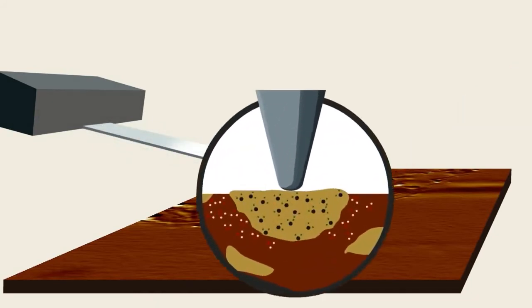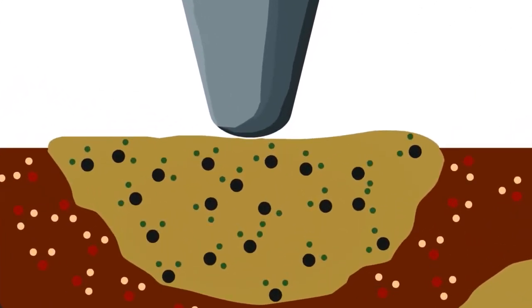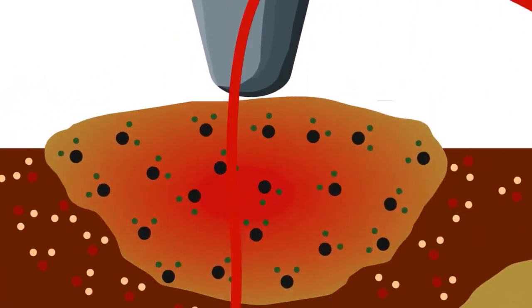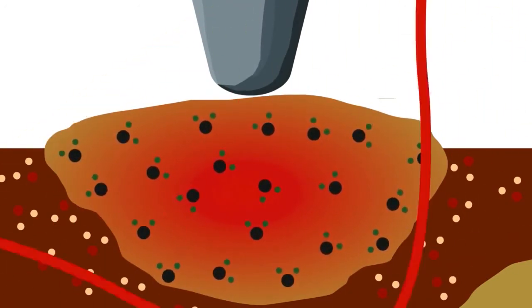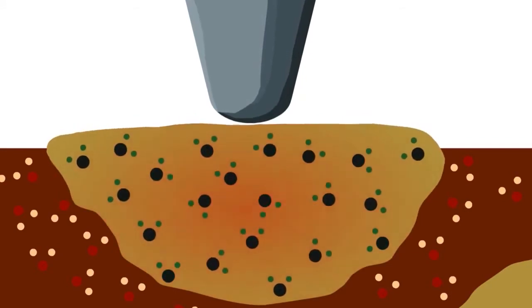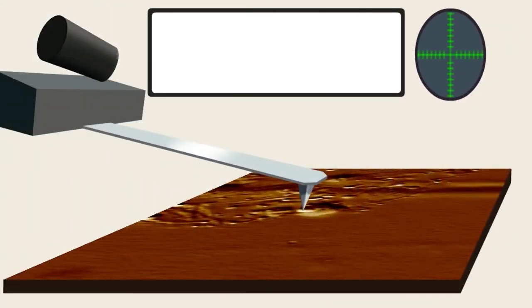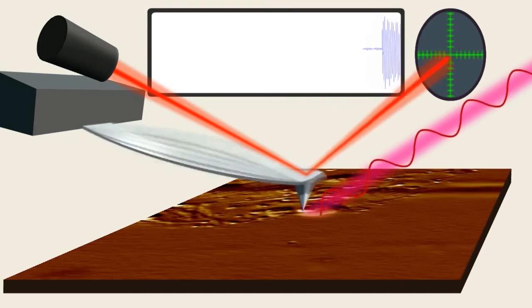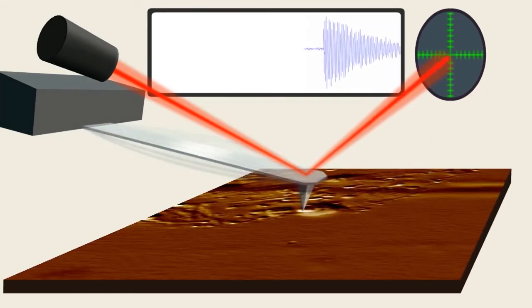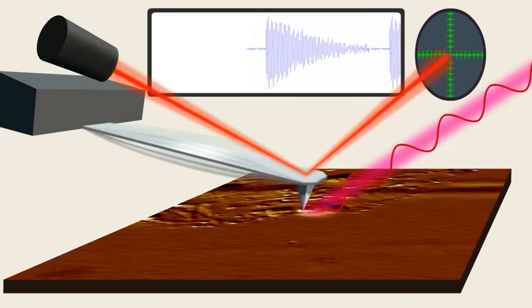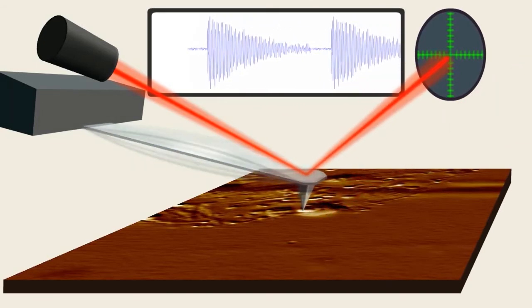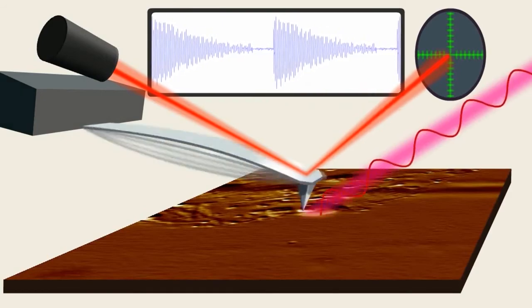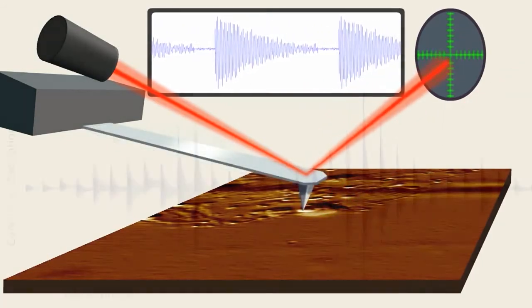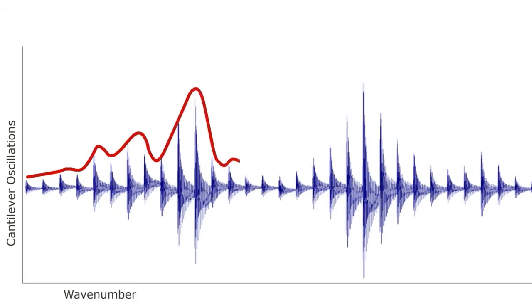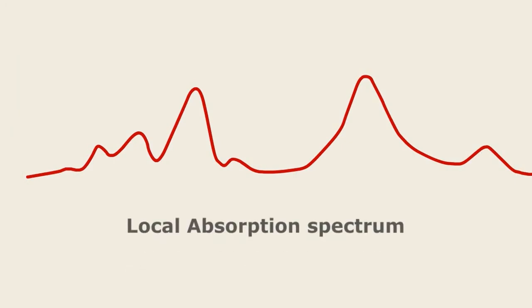And if we've tuned to a wavelength where the sample absorbs, we will start exciting these molecules, exciting the molecular bonds in those molecules, and that absorbed light turns into heat that causes a thermal expansion that pushes up on the tip of the AFM. So now what we do is we record the oscillation of the cantilever as a function of wavelength, or a function of wave number, as we're sending in these pulses of light. And then we can create an absorption spectrum simply by tracing the envelope of these cantilever oscillations as a function of wave number.